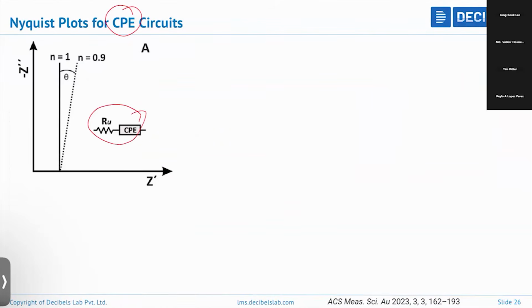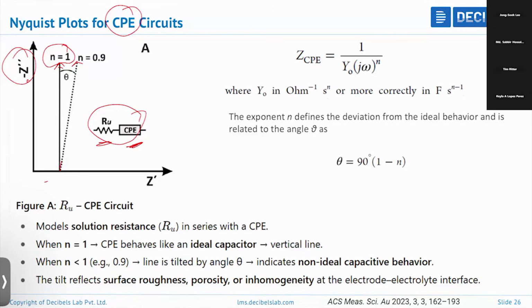If it is a real capacitor, we get a line parallel to the minus imaginary axis, like the one we have discussed, but we always get a slightly tilted line. This is because of non-ideal behavior of the capacitor, which is represented by CPE. If the resistor and capacitor are in series, we get a Nyquist plot like this. This is the impedance equation for CPE. If n is equal to 1, it's an ideal capacitor. Since there is a tilting, it is deviating from ideal behavior. There is a tilting in the angle of the line which is parallel to the imaginary impedance.